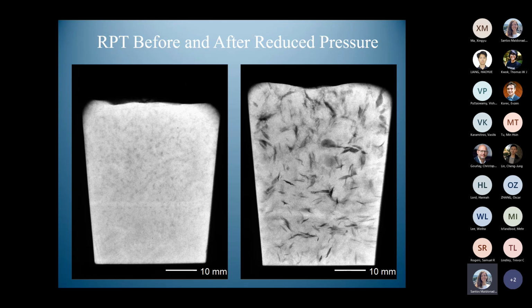And sure enough, they popped up, and you can see it's absolutely crammed with cracks that we didn't know were there. Now, interestingly, this is the same metal, poured at the same time, the same temperature, same everything, except just a different pressure. Now, the reason is this, that when we form the bifilm initially, and we fold over or we impinge the 2 dry sides to make a crack that goes off into the liquid, there's always enough turbulence beneath the surface to do this.